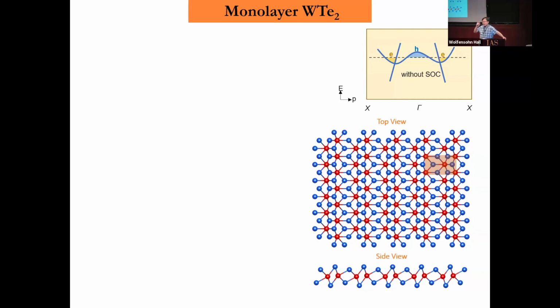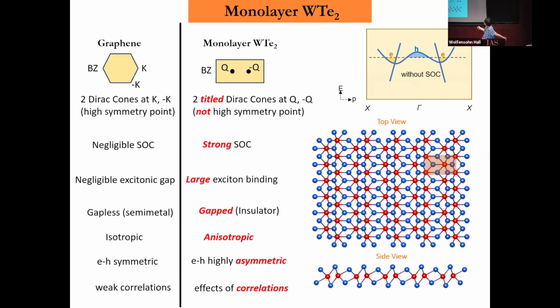But it's very different from the other TMDs that you have heard a lot about, because this is distinct from the stable ones that most people are studying, which have a hexagonal structure, those 2D semiconductors. This is not a unit cell with a hexagonal structure, it's a unit cell with a rectangle. You see, this is one unit cell. That's the key difference. So it's very different from graphene, very different from semiconductor TMDs. There's a side view. This is still the TMD of tungsten and tellurium, but they are arranged in a very different way. As a result, the unit cell is a rectangle, so the Brillouin zone is also a rectangle.